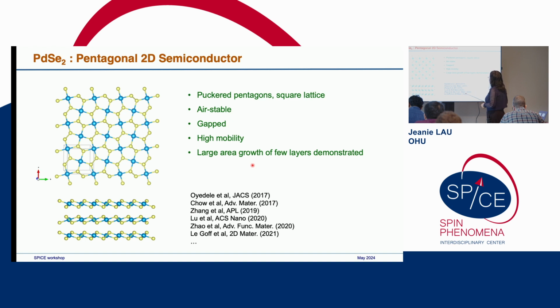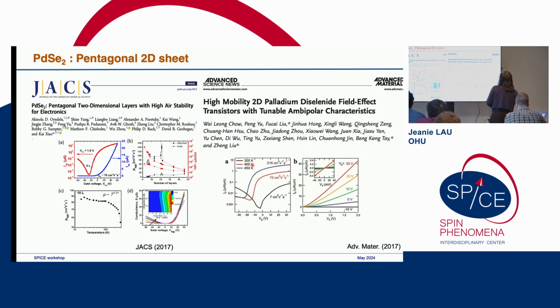So this is a layered material. Again, we can exfoliate it. There are a number of works in this area which show these claims: it is air stable, it is gapped, and has high mobility. What they call high mobility here is up to about 200 centimeter square per volt second, and it's usually done at very high bias and at room or high temperature. But large area growth of thin layers has been demonstrated. Okay, so there's some recent work.